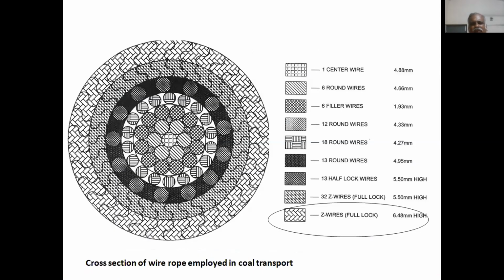The rope is basically 64 millimeter diameter and it consists of several rounds of fine round wires cross-section wise, and the last 2 outer sets are basically locked coil wire in the form of Z shape, so that they can lock each other and therefore they will be tight. But it is this Z-shape cross-section wire which is actually failing. How is it failing? It comes out. When it comes out, the bucket which travels will get stopped, and after some time it tumbles down and it is dangerous. So therefore, we were given this failed piece.